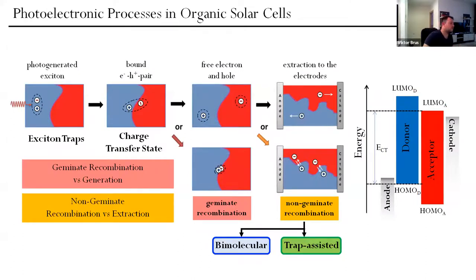So now let us focus more on understanding how organic solar cells work. That is a bit different from silicon solar cells, and we need to highlight these moments. And that's also to address your previous question, how we can generate charge carriers in organic semiconductors. So as I said before, we create an exciton when we shine light with energy larger than the band gap, the distance between HOMO and LUMO. And because of strong electrostatic interaction between hole and electron, we cannot split them efficiently because of low dielectric constant. So what we need is a bulk heterojunction, means we need a mixture of two organic semiconductors,